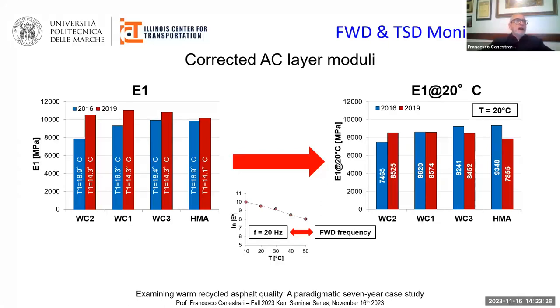This correction was made by considering the complex modulus isochronal curve at 20 Hertz that corresponds to a typical FWD load frequency response. Looking at the graph on the right, we can observe that in 2016, the hot section exhibited the highest modulus while the WC2 section exhibited the lowest modulus. Whereas in 2019, all warm mixtures exhibited a similar modulus, very similar to the ITSM results, whereas the modulus of the hot section was lower.